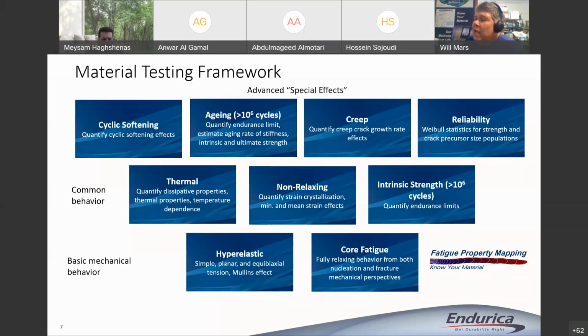So, in rubber, we're very concerned with the nonlinear elastic properties of the rubber. So we use hyperelasticity. We're concerned with steady state cyclic behavior when we're working with fatigue. We're also concerned with what I call the core fatigue behaviors. So basically that would consist of a crack growth rate curve, and it would consist of a crack nucleation curve. So we do both of those kinds of experiments in order to prepare for doing analysis, and that's kind of the basic level. And then on top of that, you can add what I would say is common behavior, but you don't always have to think about these things.